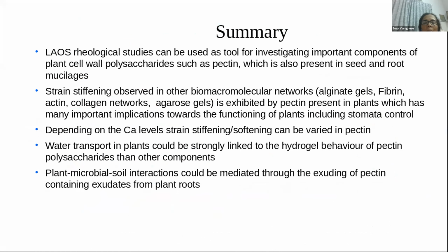So I'm summarizing here. We did what is known as large amplitude oscillatory shear rheological studies, which can be used as a tool for investigating important components of plant cell wall polysaccharides, such as pectin, which is also present in seed and root mucilages. Similarly, strain stiffening has been observed in other biomacromolecular networks like alginate gels, fibrin, actin, collagen networks, and agarose gels. All these people have shown that they exhibit strain stiffening. It is present in pectin also, which is present in plants, as I have mentioned already. Depending on the calcium levels, strain stiffening or softening can be varied in pectin. Similarly, water transport in plants could be strongly linked to this hydrogel behavior of pectin polysaccharides rather than other components like cellulose, hemicellulose or lignin.